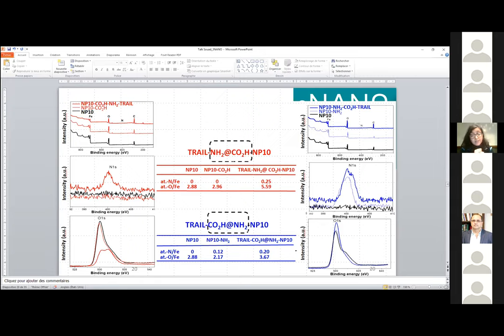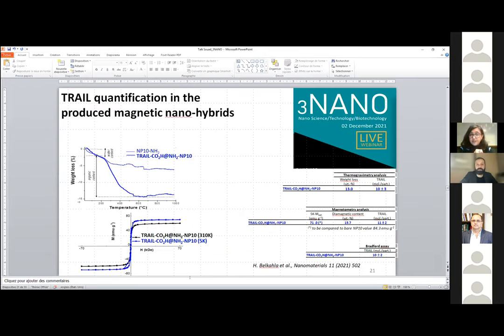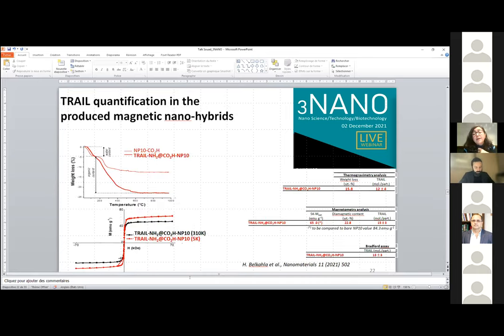We confirmed the grafting using, once again, X-ray photoelectron spectroscopy. And you can see that in both cases, we have an increase of carbon, oxygen, and nitrogen signal intensity, meaning that we succeeded the grafting. And then we performed the quantification of TRAIL using, once again, thermogravimetry analysis, magnetometry, and Bradford assay. And we obtained almost 10 molecules per particle for both cases, for the particles modified by carboxylic group and particles modified by amino group.